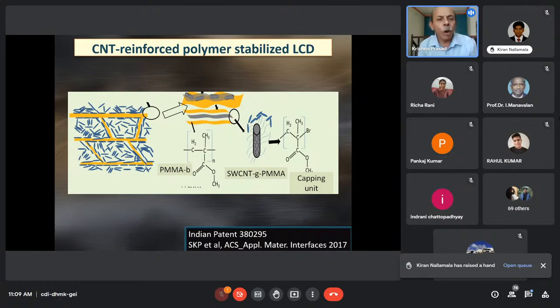But probably what I'm going to spend a little time on is how we could actually reinforce these polymers. Why one had to worry about reinforcing the polymers? When I talked about the PDLC, because of the larger polymer content, the mechanical rigidity of the system is pretty large. But when you are talking about systems wherein the polymer concentration is low, then what you are going to see is the mechanical rigidity is seriously compromised because of the low polymer content. So the idea was to see whether you can somehow increase the rigidity of the polymer without increasing the concentration of the polymer. The standard kind of polymers that can get into a liquid crystal do not work at all. You cannot just change the chemical architecture of the polymer and then get these kinds of mechanical rigidities.